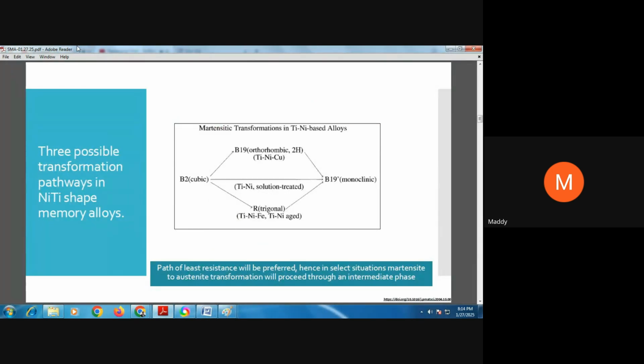As far as NiTi is concerned, the majority of our talk will be on NiTi because that's the most successful alloy, so we'll focus on that. There are three pathways for the phase transformation to happen in NiTi, depending on a couple of factors. One is the addition of ternary elements. When you add a third element, for example iron or copper, you will have an intermediate phase through which the phase transformation occurs. Alternatively, based on your heat treatment, aging, cold working, annealing, you will also have an intermediate phase called R phase. So there are multiple pathways through which the transformation can proceed from a high temperature phase, the austenite, to a low temperature phase, the martensite monoclinic structure. Long story short, the path of least resistance will be preferred by the alloy. So you can tailor which treatment you want and how you want the transformation to proceed. Next slide, please.